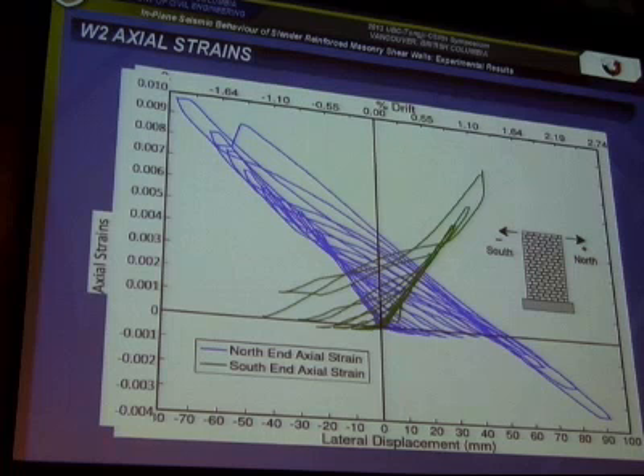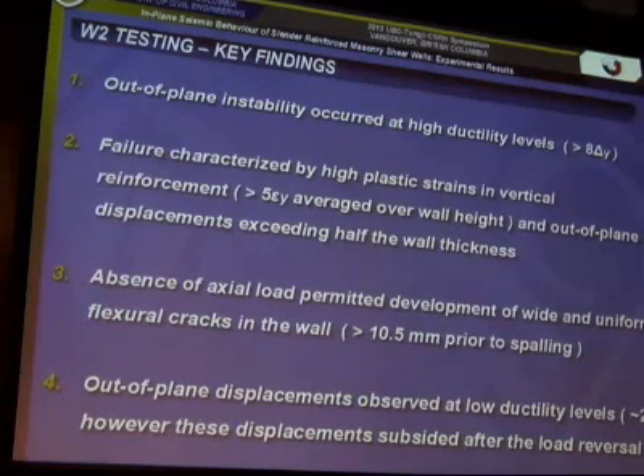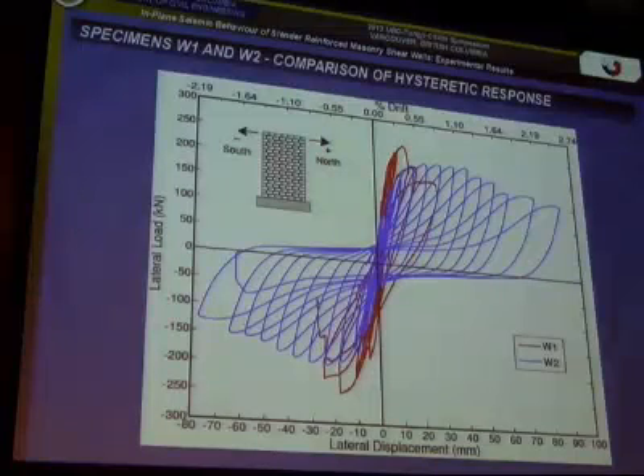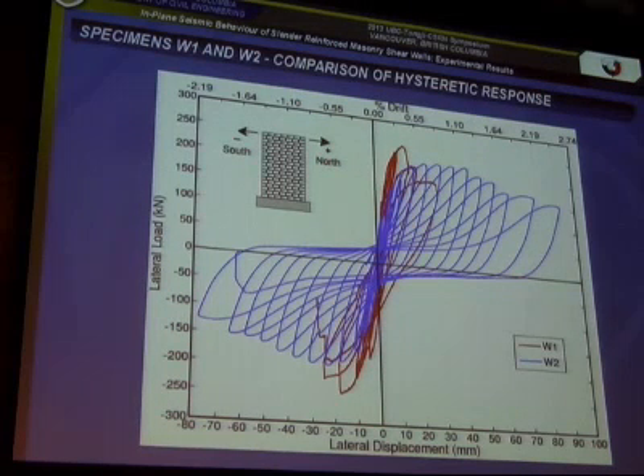Looking at the axial strains, we can see that, again, they go up to around 5 times the yield strain in the most exterior reinforcement, and so quite a bit more than the first test. Our key findings here were that the out-of-plane instability occurred at high ductility levels, and that the failure was characterized by the large vertical tensile strains, and when the out-of-plane displacements increased beyond that critical limit of half the wall thickness. The absence of the applied axial load seemed to increase the probability of this failure happening. And although the out-of-plane displacements were observed at low ductility levels, they did not become critical until much later on.